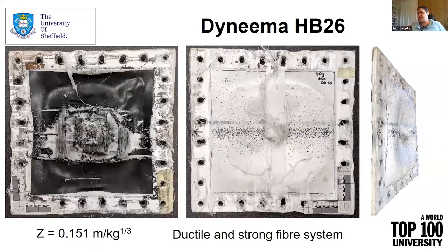During the transient response, quite a large hole opens up, but when the material rebounds, which is obviously what we've got photographed here, you can barely see the hole that's put in this panel, but I can promise you that it is there, but it virtually closes over. When you look at the broken fibers in a bit more detail using SEM, you can see tensile stretching, necking and fibrillation. And there'll be an upcoming paper on this as well, as the Australians are putting the finishing touches to their modelling of this phenomena.